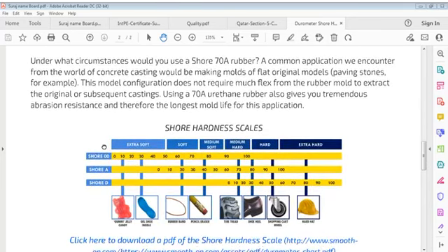In what other circumstances would you use a Shore 70A rubber? A common application we encounter is from the world of concrete casting, which would be making molds of flat original models, paving stones for example. This model configuration does not require much flex from the rubber mold to extract the original or subsequent castings. Using the 70A urethane rubber also gives you tremendous abrasion resistance and therefore the longest mold life for this application.